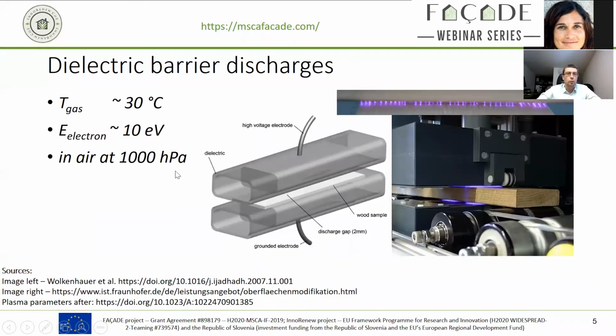So if we take a more in-depth look onto these, this is a typical way, on the right-hand side, of how this looks with a wood sample that's treated. This is an image provided by colleagues in Göttingen. And it's always essentially the same kind of setup. The electrodes are housed within an isolator, like a ceramic piece, and the wooden sample is treated in between.